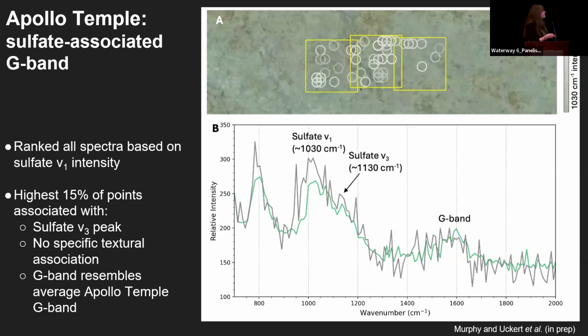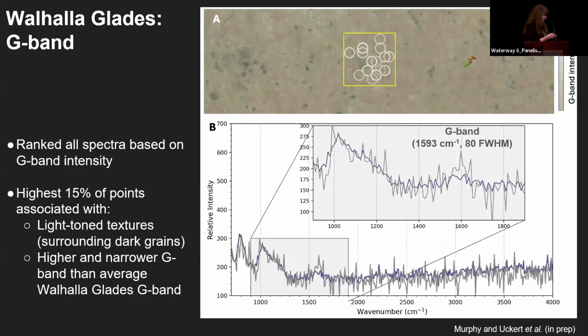We also pulled out a bit of a sulfate signal using the same process. So this is a bit of a stronger sulfate signal compared to the average, but the G band associated with that just looks like the average G band roughly throughout the whole spectrum here. And again, it's just kind of scattered throughout the rock and it's not really associated with any particular texture. And finally, we did it for Walhalla Glades, the same thing. We looked at the most intense G band points, and what we found was they were associated with the lighter texture of the rock and not these darker grains.